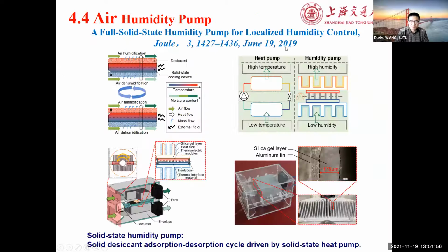And also in Joule, we published several papers. This one is for localized humidity control with a solid-state humidity pump, actually using a thermoelectric system. We try to pump moisture from a low-humidity environment to a high-humidity environment. That's similar to a heat pump from low-temperature heating to high-temperature output.